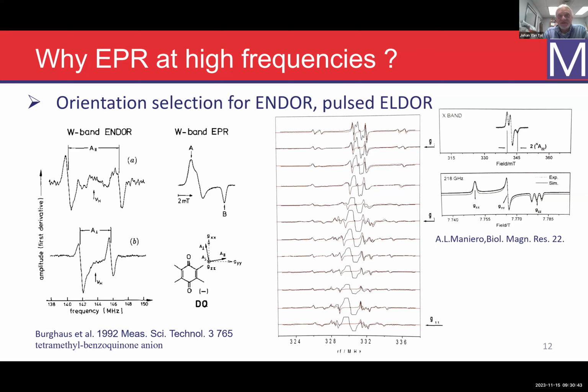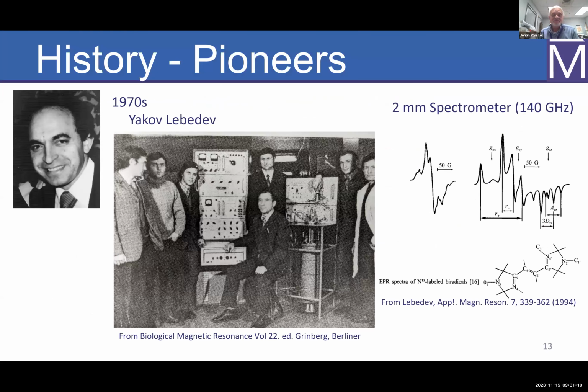So that gives you, with the higher resolution, a way to do your orientational selection. And that can also be the case for things like ELDOR. So if you do DEER measurements where you're looking at distances and distance distributions, there might be some orientation dependence to that as well. So that is something that you can use for DEER type measurements.